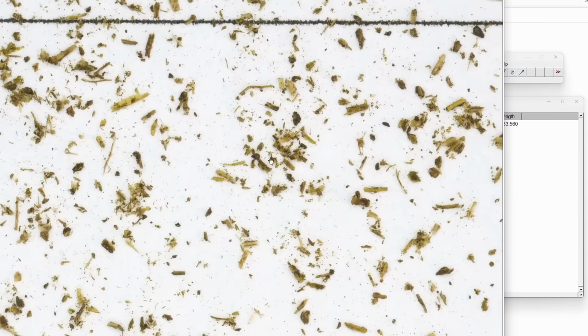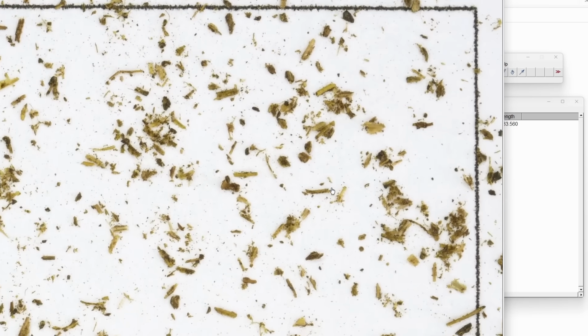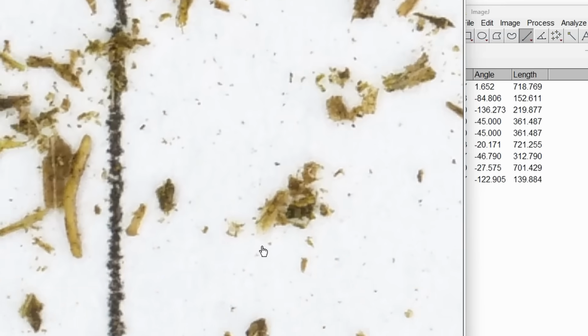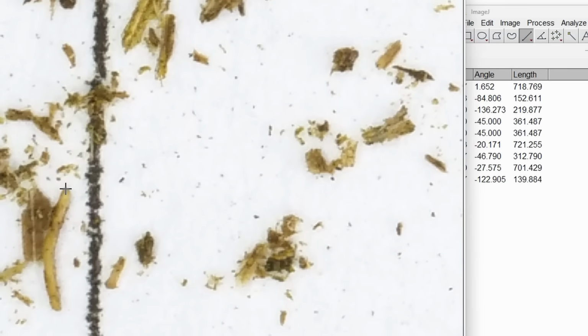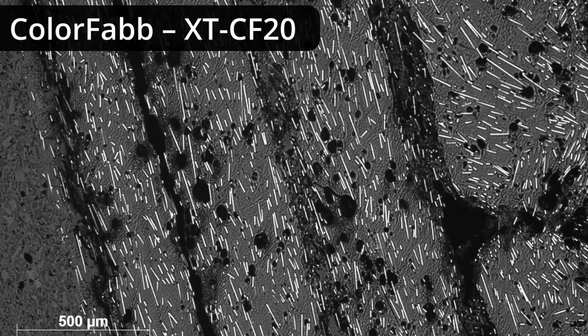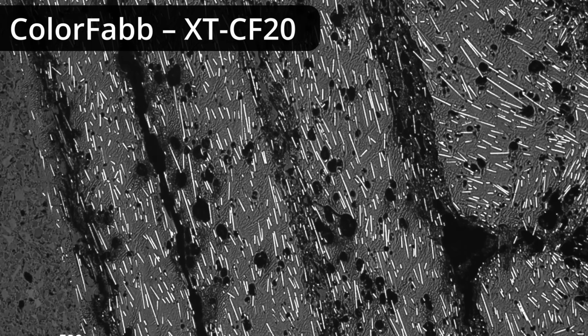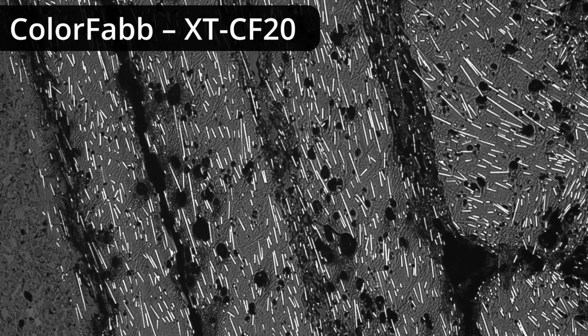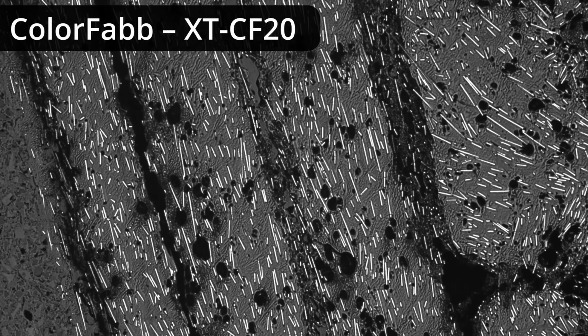It's really interesting to look at the fibers under a microscope because you can see a fascinating mix of very fine material along with some of the old grass fibers. When measured, it's interesting to find that they are sometimes over a millimeter long, but their width usually falls within the 0.25 millimeter mesh size of the sieve. This shouldn't be a problem for printing because these short fibers typically align with the flow of the material, so even something that is longer should go through the nozzle in the end.